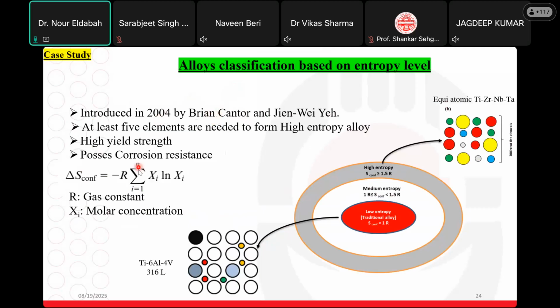You can classify them based on the configurational entropy, which is a function of the chemical composition or molar concentration of the alloys. It gives you the configurational entropy of the alloy. So what is the difference? For example, for Ti-6Al-4V, we have an obvious matrix of the alloy with some addition. We need to put some addition in this alloy to promote a certain characteristic.